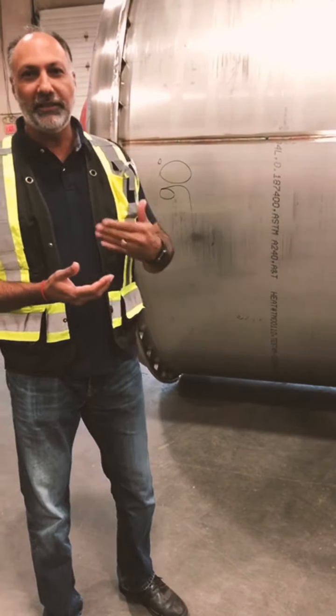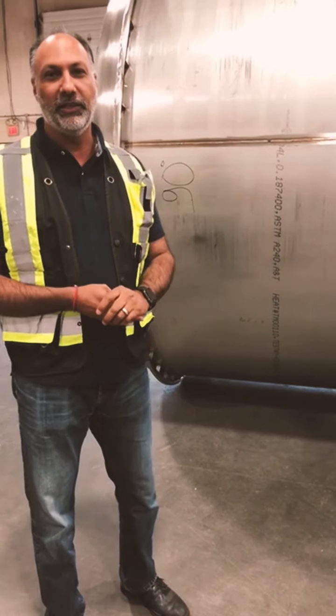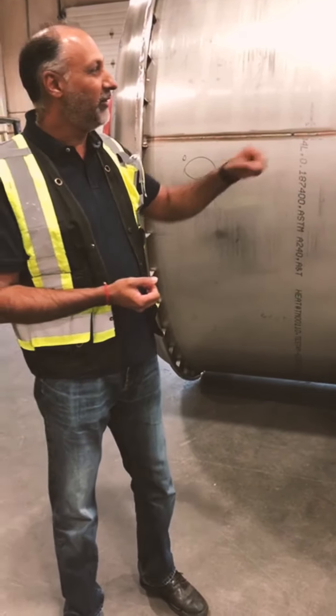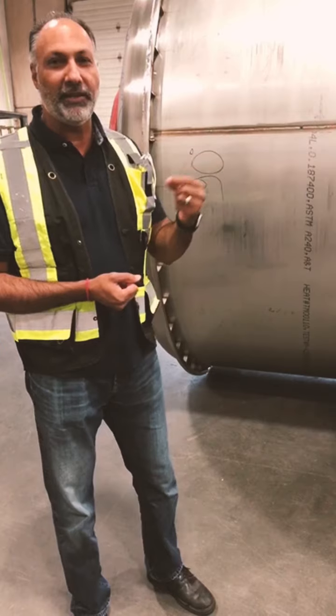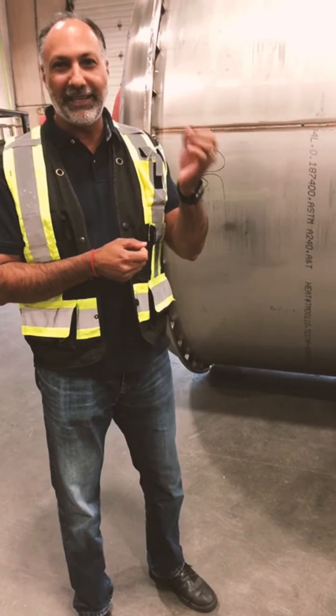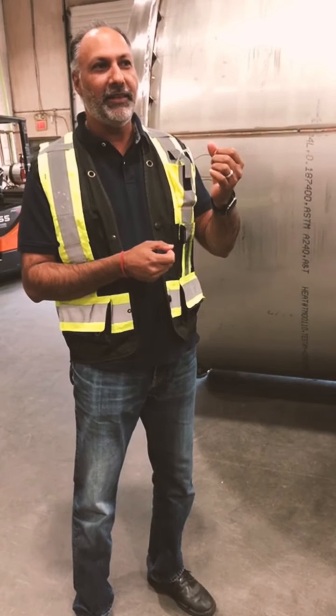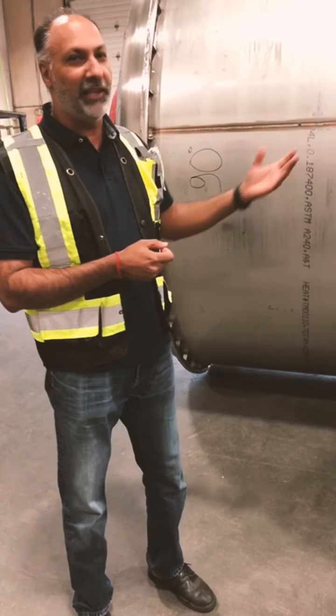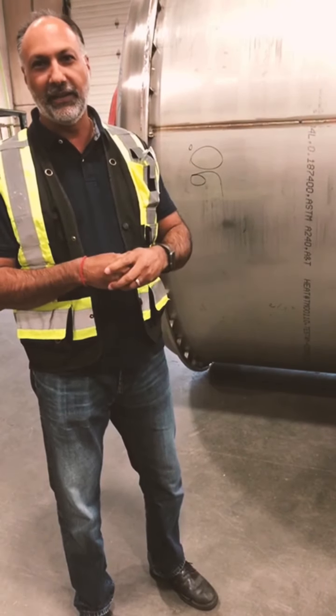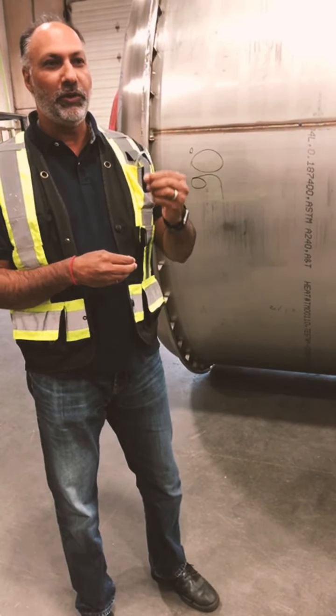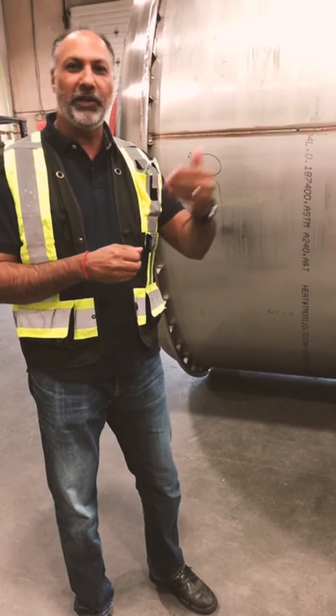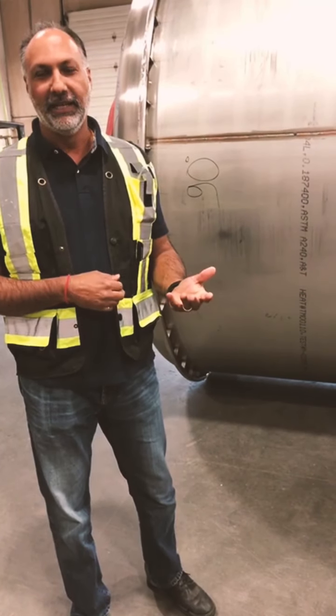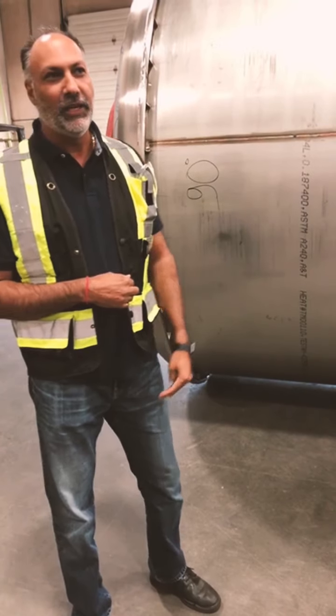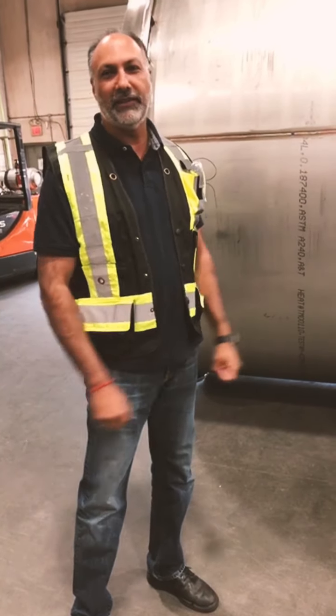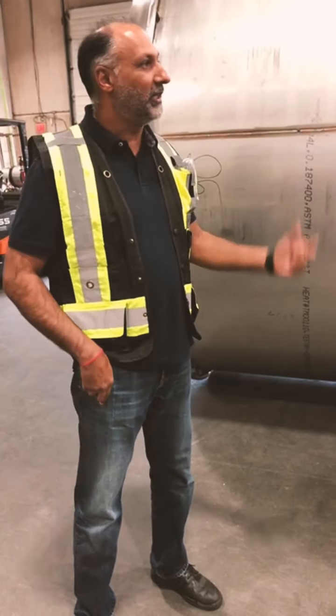So there's lots of issues, depending on what they are, like burn through, or if there is porosity. Porosity can cause, because basically there are bubbles in the weld, and then over time, due to the stresses of the tank being under pressure and not being under pressure, they can form cracks that can go either inside or outside, and then you can have leaking. So definitely at the end of the day, you have a vessel that will not last as long if you have those issues with the welding.